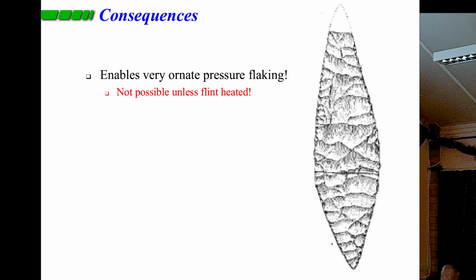This is a Solutrean industry flint axe. It would have started with something like this, which you can see is very, very crude. But if you heat the flint and then pressure flake it, you can make this wonderful laurel leaf, which is about so big. It's about so thick, really, really thin. We don't know what it was used for, of course. Probably had some ceremonial use. It was too thin to be much industrial use, but it certainly makes a hell of a difference. So now we know how Stonehenge man used to cook his flints.